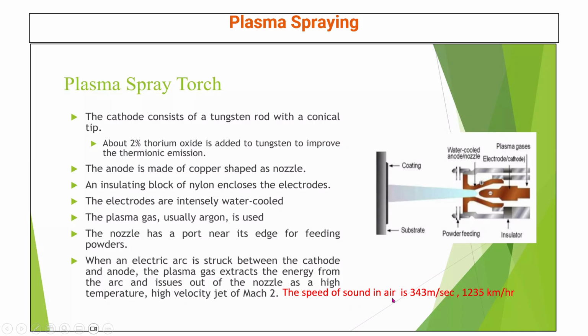Two Mach velocity means sound velocity is how much? 343 meter per second, or 1235 kilometer per hour. With 2 times, nearly 700 meter per second velocity, the material will go and get stuck on the surface coating, with high temperature and high velocity. So this is also the plasma coating that will be there on the surface.